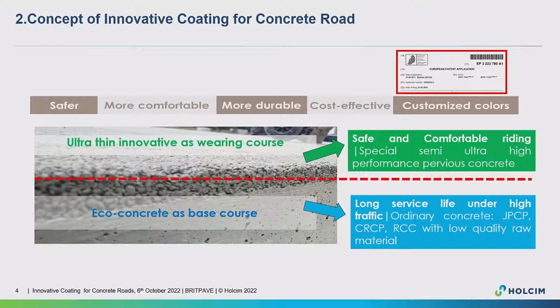Our laboratory studies carried out from 2015 to 2018 showed that by using this structure, we can have a safer structure, because it can help to avoid the aquaplaning phenomenon with the splash and spray waters. It's more comfortable because the top layer is placed by the vibrating table or vibrating screed, so it has a negative macro texture. It's a connected void structure, so it's less noisy than the gap dense or the ordinary concrete. For sure, it's more durable because we use the polymerized cement to make our semi-pervious concrete. In terms of mechanical strength, the top layer, the semi-pervious concrete, can go up to 40 or 45 MPa in compressive strength and up to 12 or 14 in terms of flexure strength.